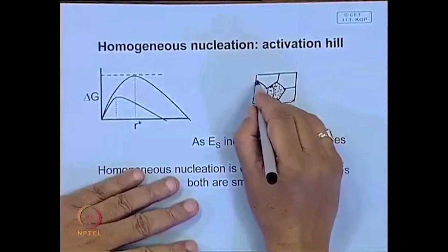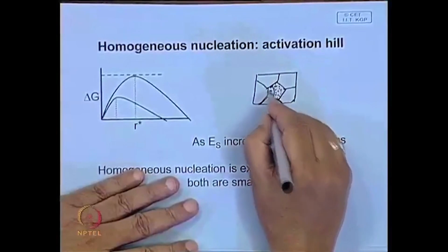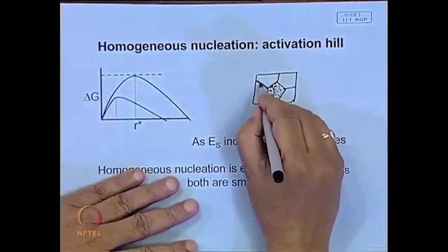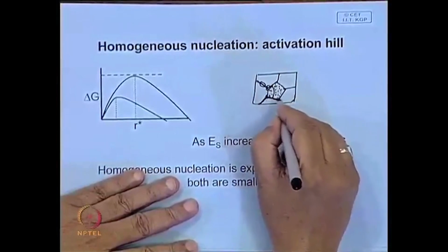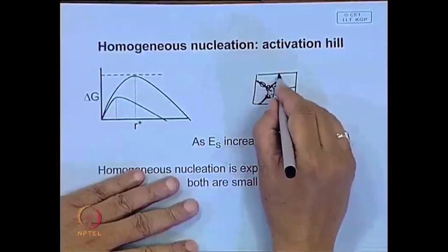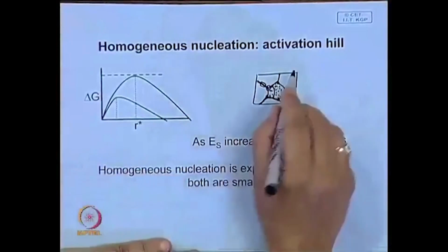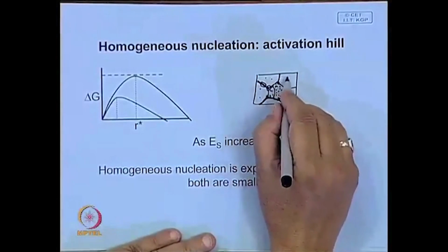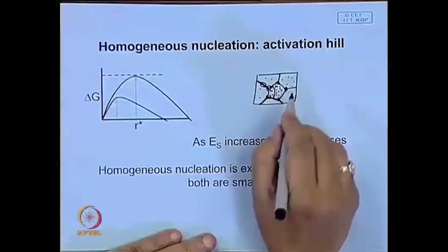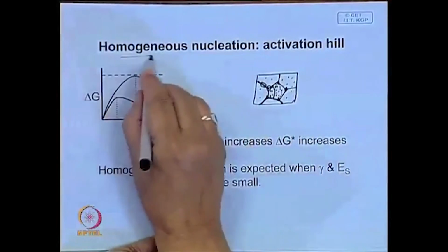You have to suppress the grain boundary, because the grain boundary provides a favorable nucleation site. Normally precipitate will like to form here, primarily at the grain corners and the grain faces. Now, to get a good precipitation strengthening, you have to have a nice array of precipitates within the grain, and this can be promoted by promoting homogeneous nucleation.